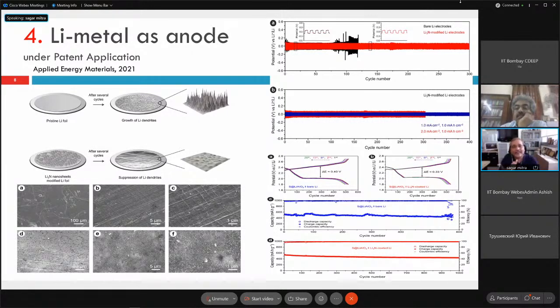The dendrite formation creates a lot of problems in the battery system. There is another solution we are working on. We are depositing some of the components from the SEI, the solid electrolyte interphase, which is the lithium surface film formation. We are taking that composition and making it artificially, and seeing that these compositions are good for long cycle life. Some cycles of 10,000 cycles have been done on a miniature time scale. You can see this is possible.